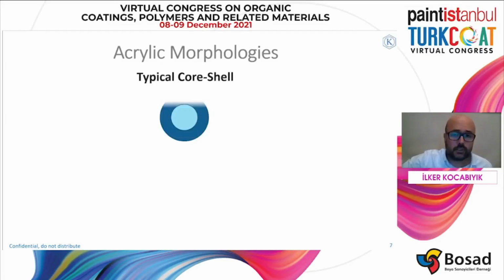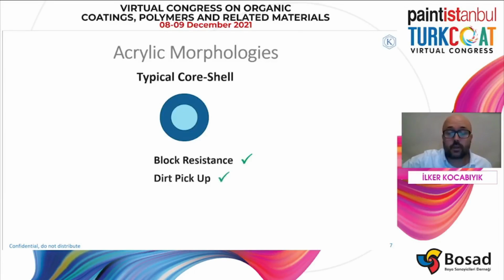As a second option, we can use heterogeneous morphology and choose a typical core-shell design where core and shell phases have more than 20 to 30 degrees Celsius Tg differences. We might expect excellent block resistance, good dirt pickup, enough cold check performance maybe not, but long-term outdoor durability will be lower due to film tension between two phases.